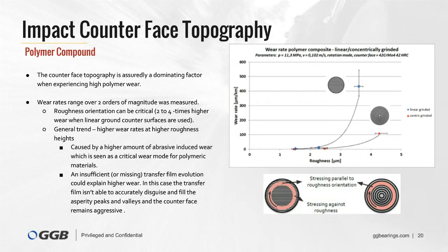Another general trend is visible that there's higher wear at higher roughness heights. This can also be explained by the amount of abrasive-induced wear actions. The rougher the counter surface, the more abrasive interactions we have. In one of the introduction slides, we explained that polymer composites need to form a protective polymer film on the counterface to reduce its wear actions. So another hypothesis could be that rough surfaces just prevent the formation of a protective film, and the missing transfer film would explain the immense increase in wear at higher roughness heights.